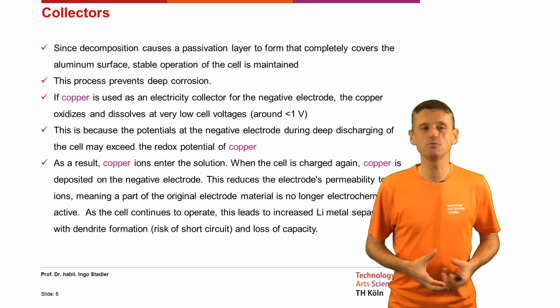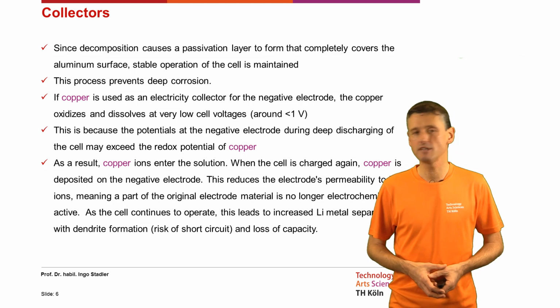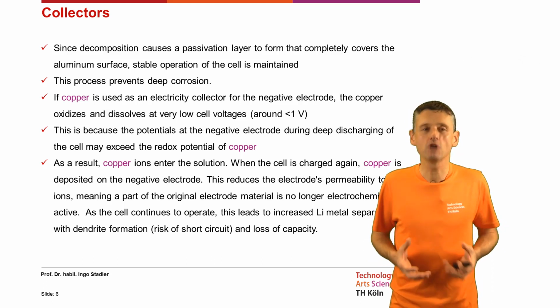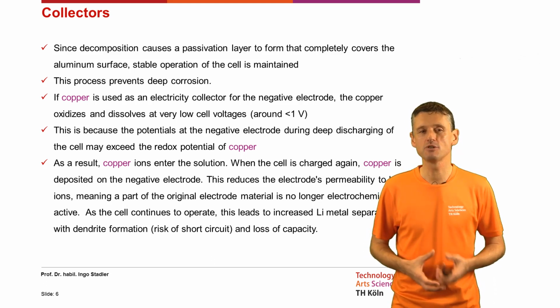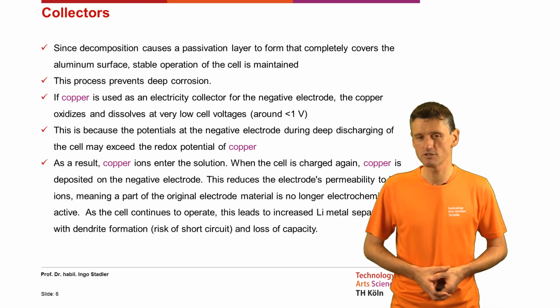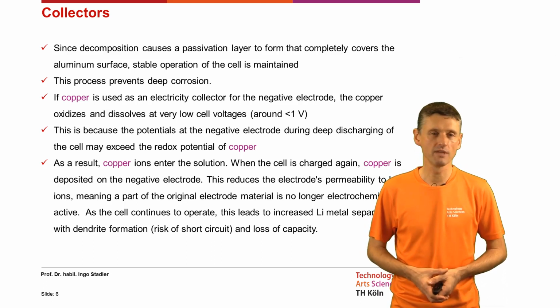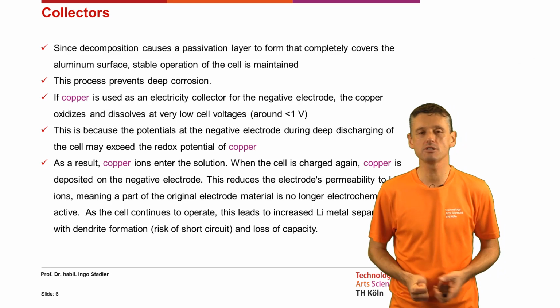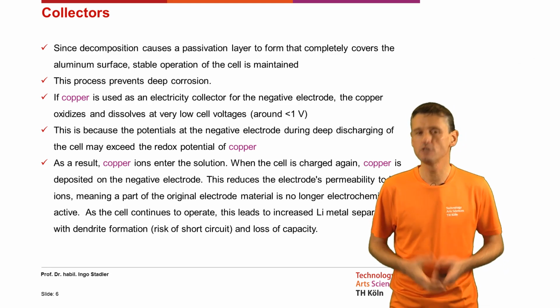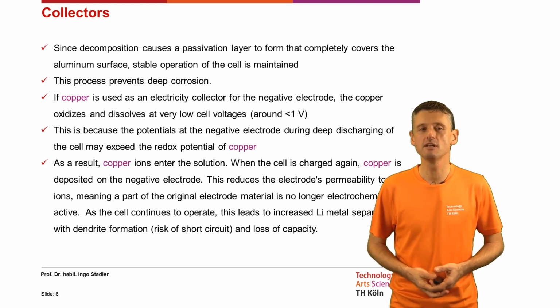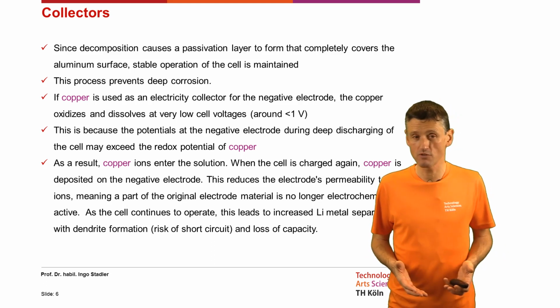If copper is used as an electricity collector for the negative electrode, the copper oxidizes and dissolves at very low cell voltages, even below 1 volt. This is because the potentials at a negative electrode during deep discharge of the cell may exceed the redox potential of copper.